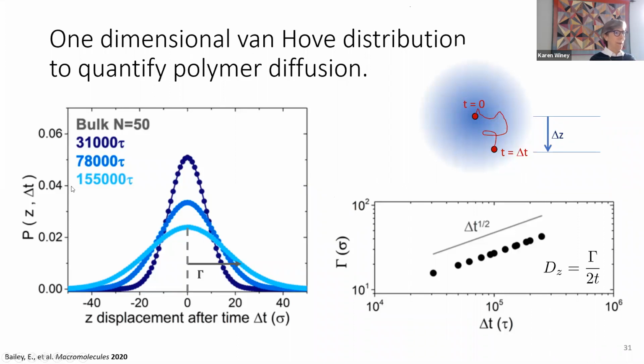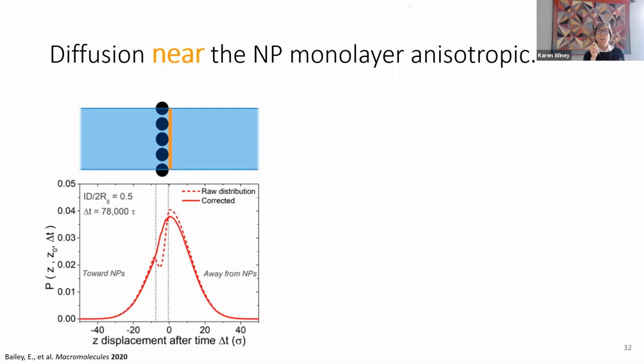And so in the bulk, these data are here for the bulk, for different times, short, longer, longest time, you can see that at infinitely short times, it is going to be a delta function around 0. And then as longer and longer time, you're going to have this Gaussian spread. You can look at the half width of this Gaussian, and plot that half width as a function of the time delay, and you get this power law dependence, and this is how we can extract out the diffusion coefficient.